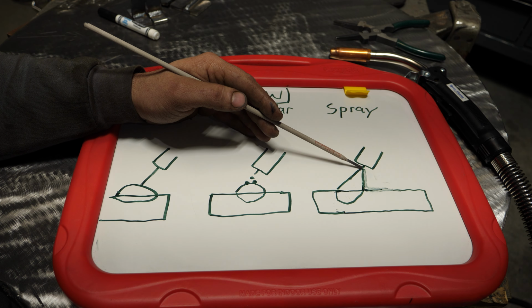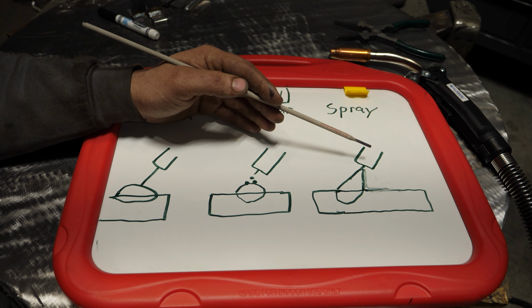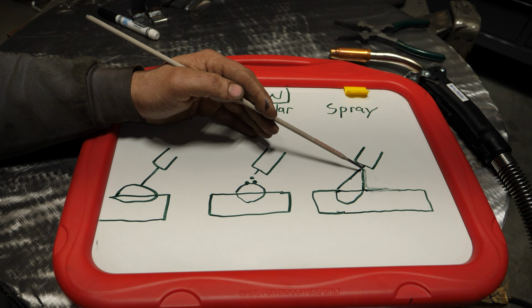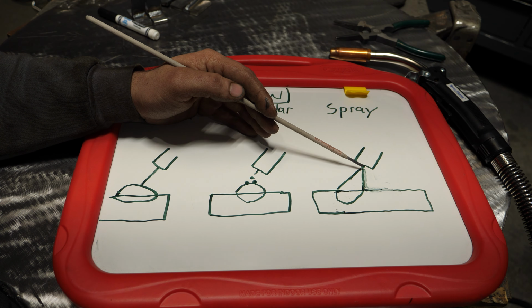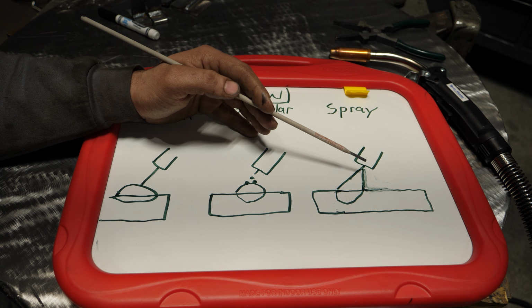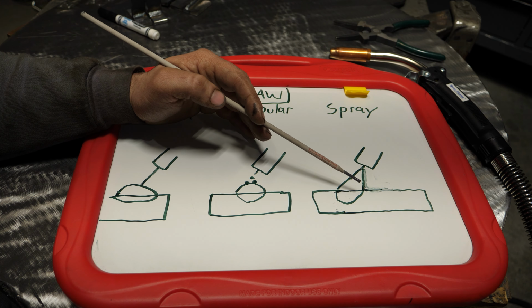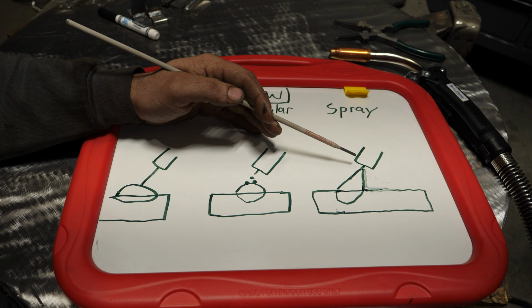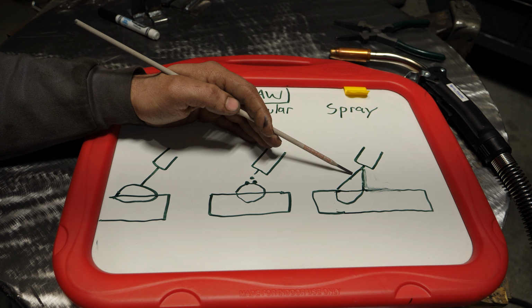And it's basically huge benefits on thicker plate when you run spray. The downside to it is you can't really weld thin plate. Like if you're trying to spray weld eighth inch material, good luck. You're going to probably burn holes and it's going to get far too hot. So spray is only generally done with 1/4 inch, 3/16 and thicker steel.